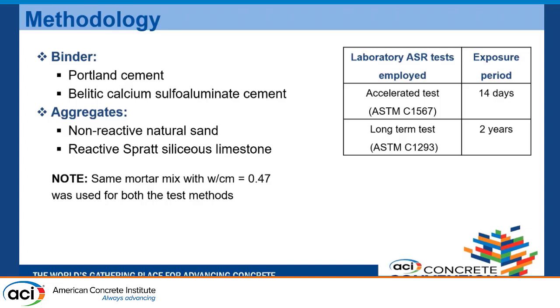I've used two cements, one is BCSA, and I've also used Portland cement specimens for comparison. The aggregates I'm using are a natural non-reactive sand, which is the control aggregate, and reactive Spratt siliceous limestone, which is known to be ASR reactive. The table on the right shows the test methods and the exposure period. For the accelerated test, the exposure period is 14 days, and for the long-term test, the exposure period is 2 years. I'd like to add that the mortar mix I've used is the same for both test methods, but in different test environments.